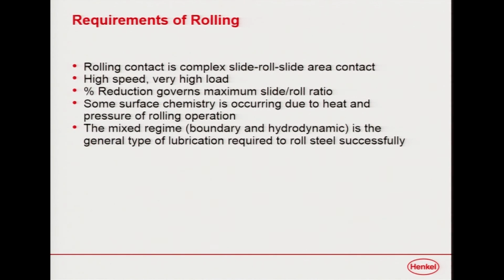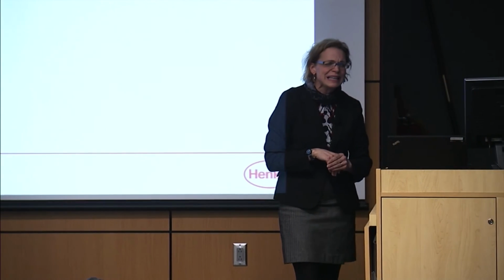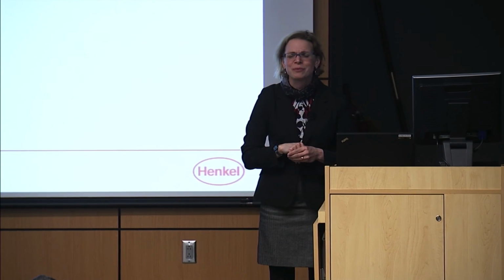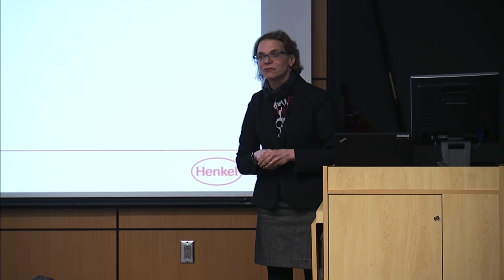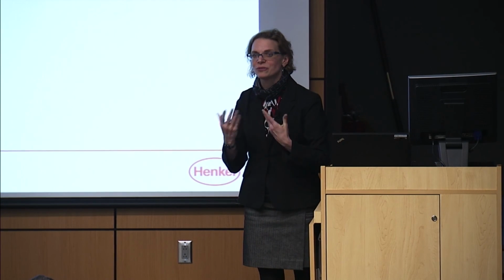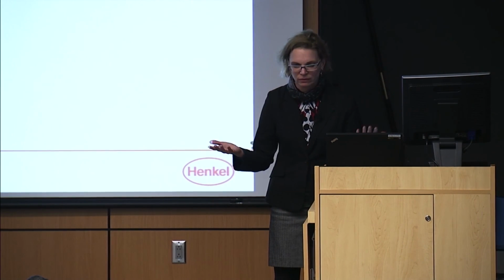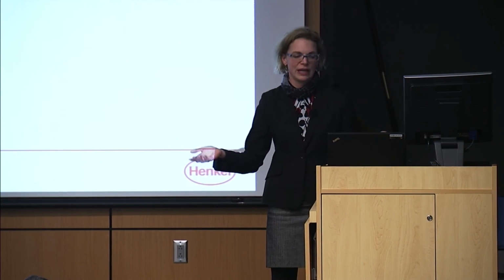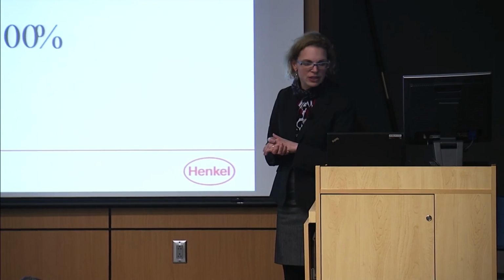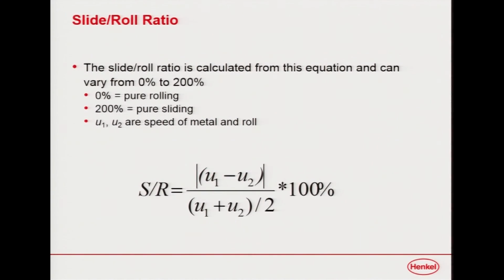So we know there's a lot of surface chemistry, and we know that there's enough heat in there that there's probably something going on. We also know it's moving fast enough that no matter how much surface chemistry you have, it's moving so fast it's a Newtonian fluid anyway. You get to a speed point where you build up hydrodynamic wedges. I mean, you actually have to. So then we look at the slide roll ratio. This is a little bit of math, which is a way of defining how far out on the work roll we can go. Like how many degrees of the work roll can we go before the steel will actually back out of the roll? It's just important to know that that exists.